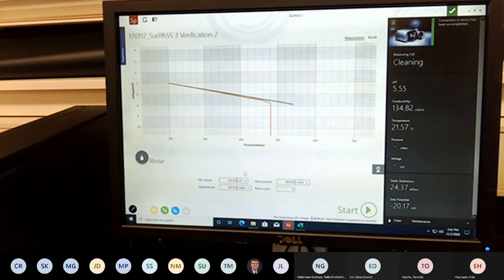These settings that you see here are pretty much the standard settings that you'll be using. So you would fill about 100 milliliters of the electrolyte solution, and then it's going to start from 600 millibar and go down to 200 millibar. Generally what you will see is more or less a straight line when this is happening. You can also select the number of rinse cycles that you want to do. I would generally recommend between 3 and 5, just to make sure that the surface is wet enough